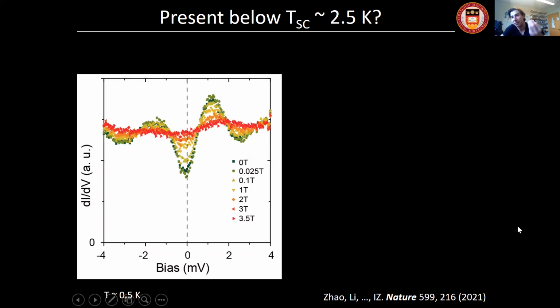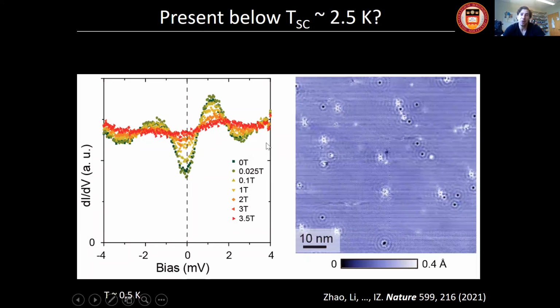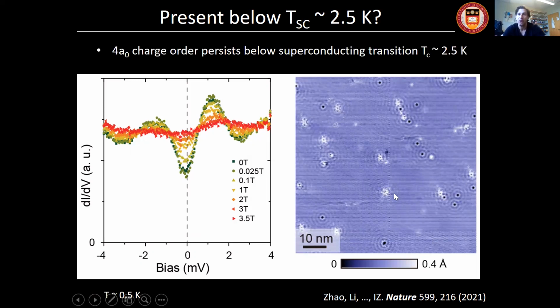But in any case, given this is a superconductor, the natural thing one might ask is, you've shown us the normal state, from 4 or 5 Kelvin to 60 Kelvin. How about the superconducting state? Do these charge ordering wave vectors still exist? So we cooled down to probably about half a Kelvin of effective electron temperature, well below the 2.5 Kelvin of the superconducting TC, and performed the same measurements. We see this 4A0 order as well. So it seems that this kind of charge ordering persists below the superconducting transition as well.